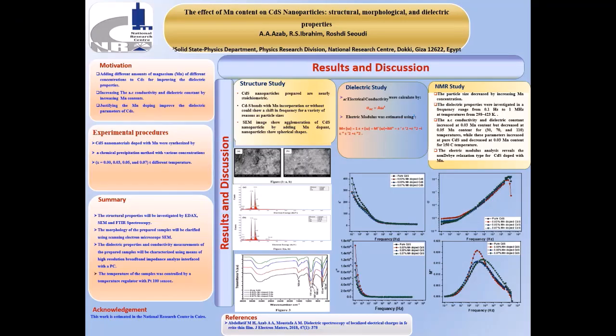Cadmium sulfide semiconductor material has a band gap of 2.4 electron volts and has several applications in high efficiency solar cells. Recently, cadmium sulfide doped with magnetic transition metal elements is called a diluted magnetic semiconductor material. In this paper, we prepare cadmium sulfide doped with manganese by chemical methods